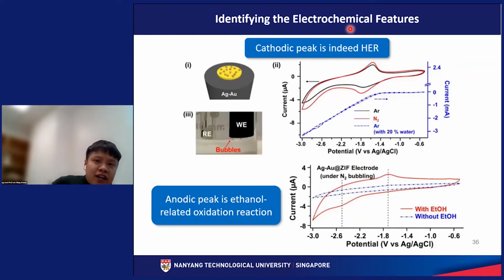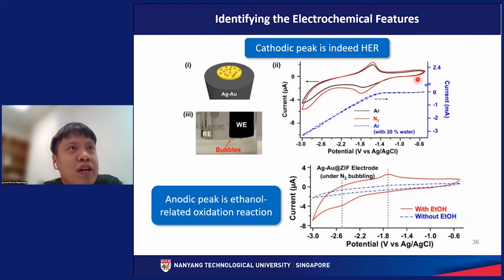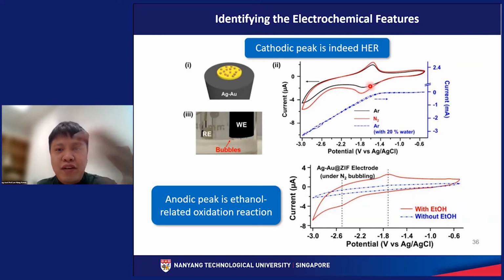So we further identify the electrochemical features using various control experiments. So if we were to spike our electrolyte with 20% water, we observe an increase in the magnitude of the reduction current. Okay, so the onset is very similar to the onset of the water electrolysis peak over here. And of course, we are able to see bubbles being formed, and this tells us that the reaction related to this peak is again attributed to hydrogen evolution reaction.